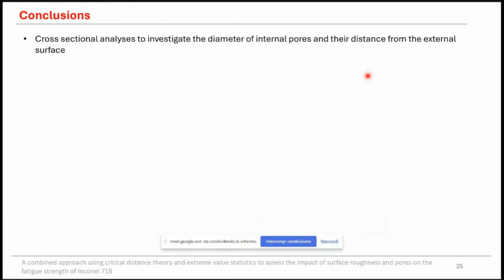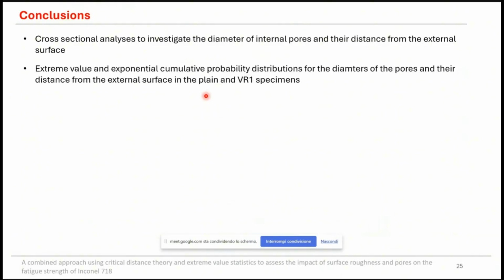In conclusion, in this work, we started by considering the role of porosities on the fatigue strength of AM components made of Inconel 718 and produced through laser powder bed fusion. We considered pore diameter and distance from the external surface. We used extreme value statistics and exponential distribution to describe pore diameters and distance from the external surface respectively. And we reconstructed surface morphology through the use of an optical profilometer.